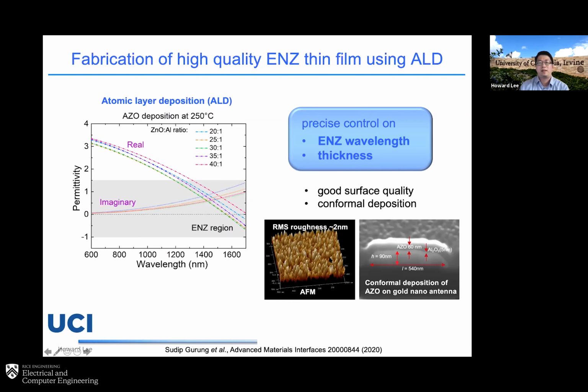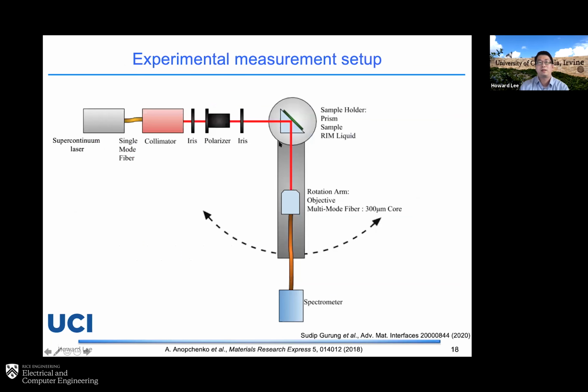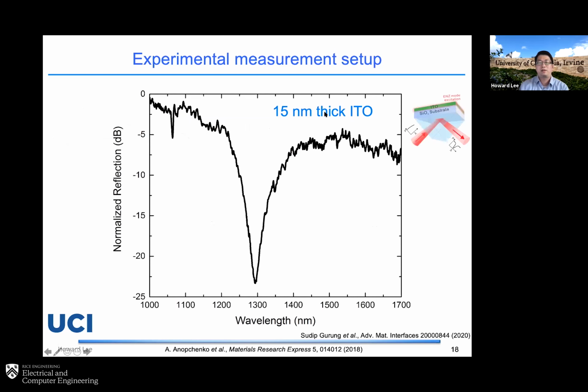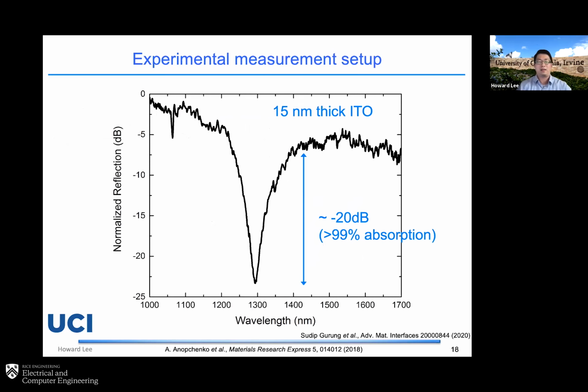So then we have been using this technique to make quite well controlled ENZ material. Once you have the good material, we put it into the setup. We have a sample here, then we have a supercontinuum light source, a broadband light source, coupled in with a certain angle through a prism, and then you can collect at different angles with a spectrometer here. And just to show you one of the ITO films we made and the measurement we see for the reflection, you see a reflection dip here, which corresponds to the ENZ mode excitation. The amplitude here is around 20 dB, which means it's more than 99% absorption. So you can see how impressive that is. You can use only 10, 15 nanometer of thin film and absorb maybe around 100% of light here.